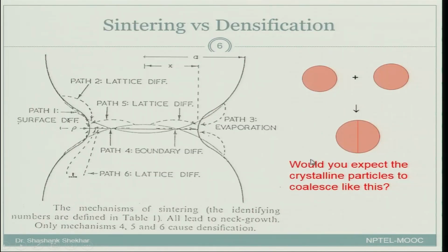Now, to re-emphasize the point about sintering versus densification, another plot is shown here. Here you are shown the two particulates. These were your two original particulates. Now, you see there is a small amount of overlap, and why is that overlap taking place? Because the center to center distance has come closer, and there are some mechanisms shown over here that define it. In the caption you can see that only mechanisms 4, 5 and 6 cause densification.